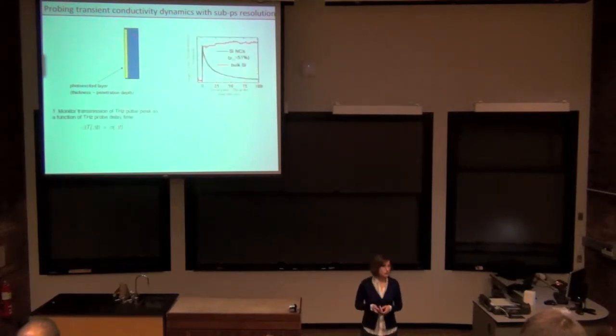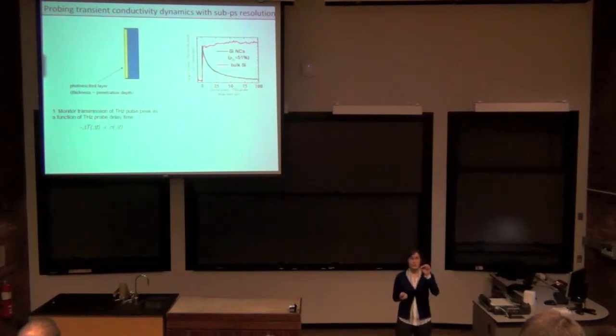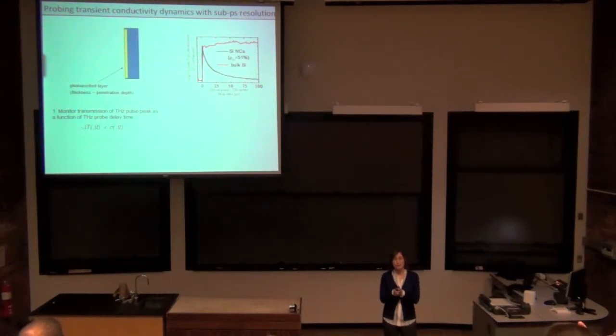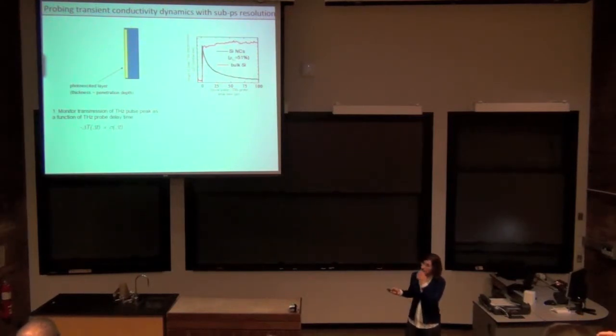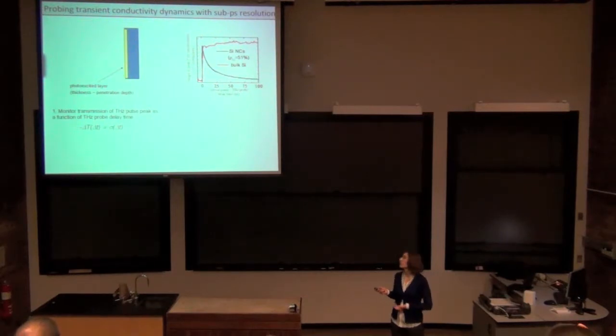There are two ways to do it. In one case, which is shown here, we just sit at the peak of the terahertz pulse and we monitor changes in transmission of the terahertz pulse as a function of the time delay between our photoexcitation and the probe pulse. It can be shown that in the limit of small modulation, where the changes in transmission are less than 20%, what we are getting is directly proportional to the photoconductivity.